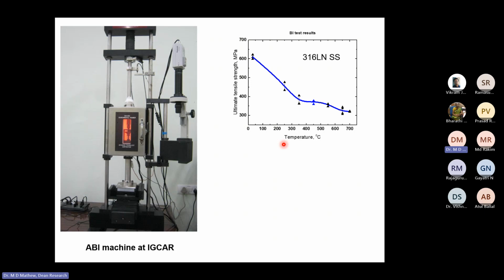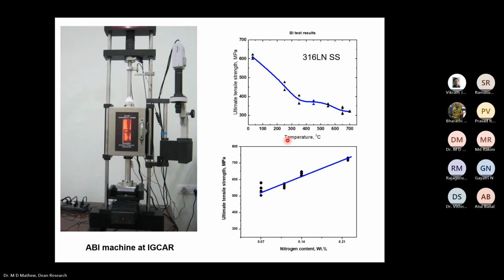So that's a very strong point. This machine is able to do high temperature ball indentation tests up to 700 degrees, and I think the capacity is up to 800 degrees Celsius. The experiment was carried out on a number of heats containing different nitrogen contents. Other element composition and grain size, everything was kept constant, but we had multiple heats with different nitrogen contents. This graph shows how the UTS varied with nitrogen content. As the nitrogen content in the heat material increased, the ultimate tensile strength also increased. And these findings were very similar to the results that we obtained from conventional tensile tests.